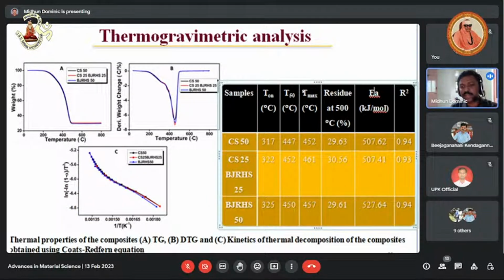And this is regarding the thermogravimetric studies used to assess the thermal stability of the material. The thermal stability is somewhat higher for BJRHS. T-on means the onset degradation temperature, at which degradation starts. T50 means the temperature at which 50% degradation takes place. And T-max means the temperature at which maximum degradation takes place. We could see that for commercial silica the T-max is 452 degrees Celsius, and here it is 457 degrees Celsius with BJRHS. So higher T-max, higher thermal stability, is for the BJRHS composite.